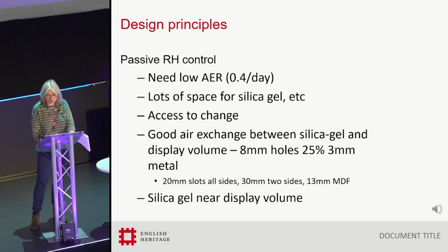8mm holes covering 25% of the base board. We use 3mm metal baseboards, perforated ones. If you do have solid baseboards, then we found that 20mm slots around all the sides work. If you've only got 2 slots available to you, then 30mm slots work, and 13mm for MDF boards. And you need the silica gel near the display volume.